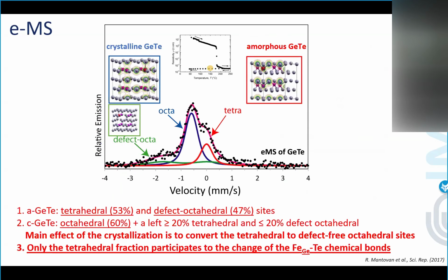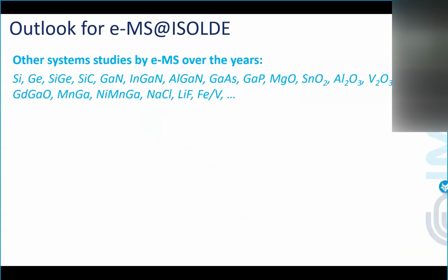So to close the story, we have been able to make, by emission Mössbauer spectroscopy, a sort of atomic-scale pictures of the amorphous phase and the crystalline phase by following it in situ. All this by putting a total of 10 to the minus 3-4 atomic percent of iron, which in these cases served as a local probe in a material that was totally ironless, okay? So, of course, matching with the theory in this case was absolutely necessary.